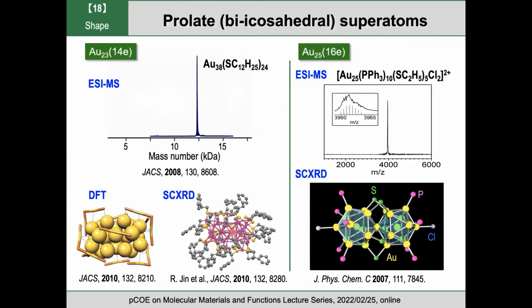And another type of bi-icosahedral core is found in gold-23, protected by the combination of 3 different ligands. And as you can see in this crystal structure, 2 icosahedrons are sharing a single atom to form a gold-25 core. And the total number of electrons confined in the core is 14 and 16.